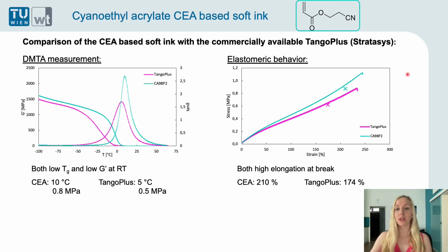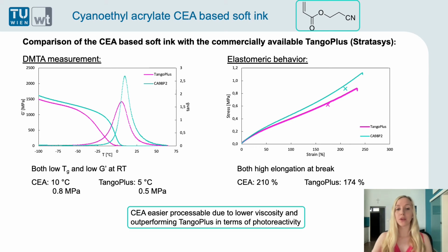of 6 measurements, and the X marks the average value. So both materials have a high elongation at break. The average value of the cyanoethyl acrylate is 210%, while the Tango Plus shows 174%, but both materials are fine in terms of elastomeric behavior. But in summary, I can say that the cyanoethyl acrylate is easier processable due to the lower viscosity, and it's completely outperforming the Tango Plus in terms of photoreactivity, which is important for our application.